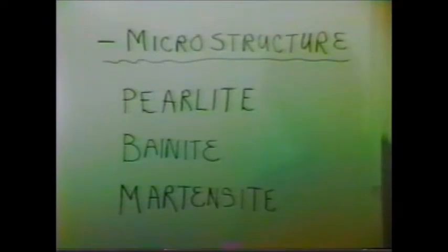The final microstructure is determined by what happens to the rejected 99% of the carbon as the steel cools from its high-temperature austenite phase to its room temperature ferrite phase. The rate at which this cooling takes place is one of the major factors in this process. 3 different types of microstructures that can be obtained with the different cooling rates of the steel are pearlite, bainite,